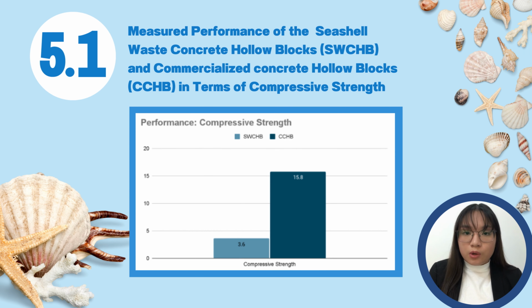Starting with Table 5.1, it illustrates the compressive strength of both hollow blocks. Compressive strength is a property that evaluates a material's capacity to sustain applied compressive loads without failing, and is tested using the standard BS EN 772-1. Therefore, an increase in compressive strength would be more acceptable. According to our data, the CCHB had a compressive strength of 15.8 N/mm², while the SWCHB had a compressive strength of 3.6 N/mm². Therefore, the commercial concrete hollow blocks demonstrated higher compressive strength when compared to the seashell waste concrete hollow blocks.